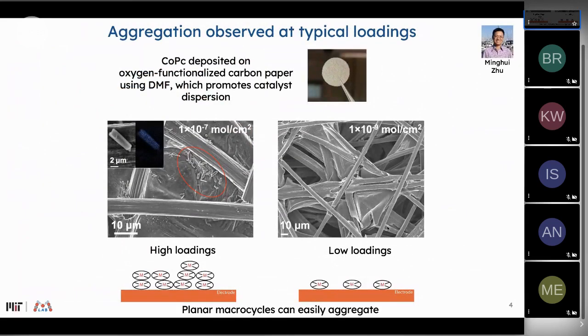So in our earliest work, what we recognized is that when we deposited the cobalt phthalocyanine catalyst and looked at this electrode with a microscope, we could actually physically see crystals on this substrate, and that's shown here on the left-hand side. Each of these is a macroscopic aggregate of cobalt phthalocyanine. Cobalt phthalocyanine is quite liable to aggregate because it's a planar macrocycle. It stacks up like sheets of paper. The metal in one macrocycle coordinates the nitrogen in the next, and you get these diagonal stacking aggregates that ultimately end up making a crystal. And these are very typical deposition conditions in the broader literature.